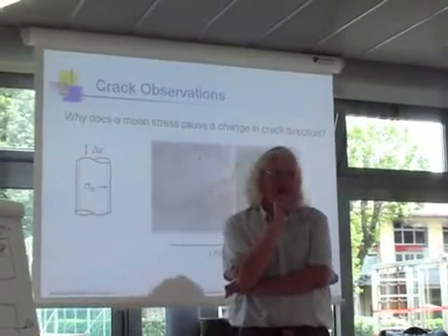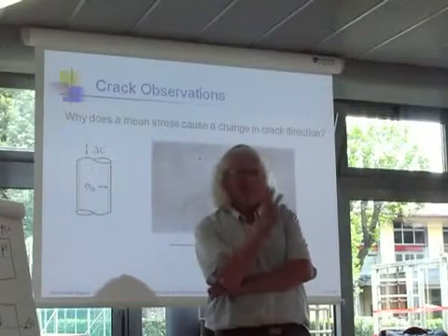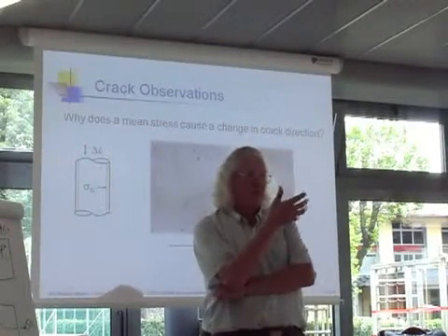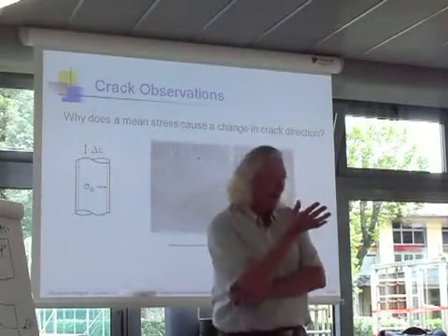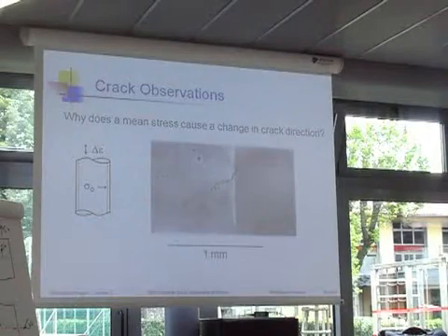So again, there's not a good universal model, right? Because the failure modes change. So when I actually analyze things, I analyze both possibilities. I always say, I'm not sure if it'll grow in mode 2 in shear or in mode 1 in tension. I analyze both of them. And then I decide if I want to be an optimist or a pessimist, which number I choose. But you know, the problem is, yeah.